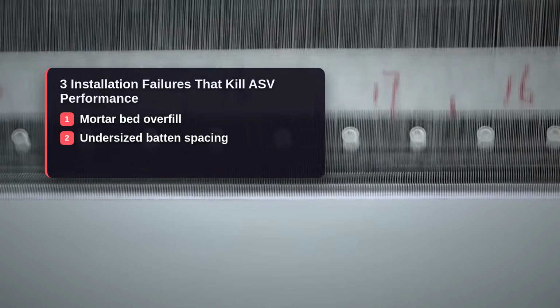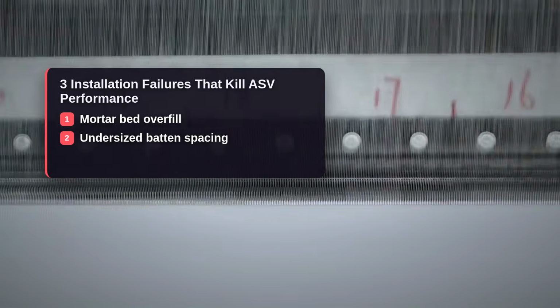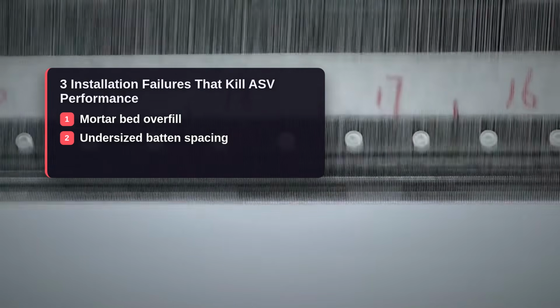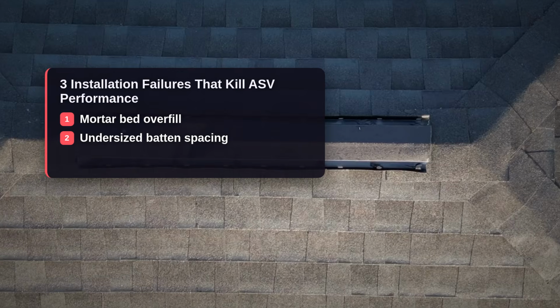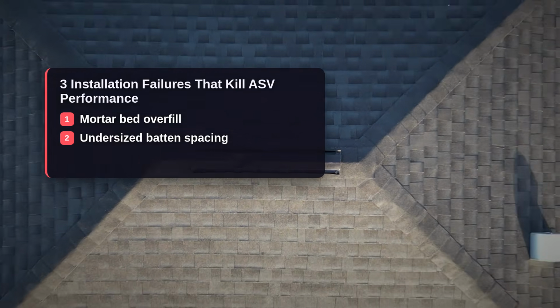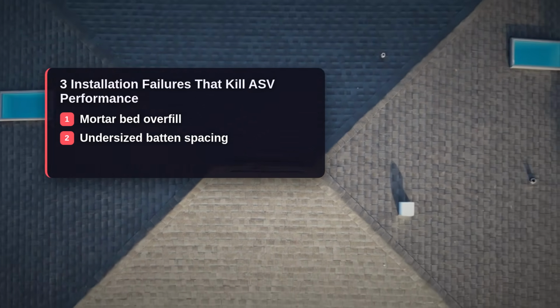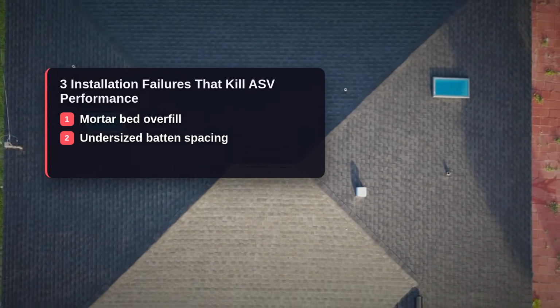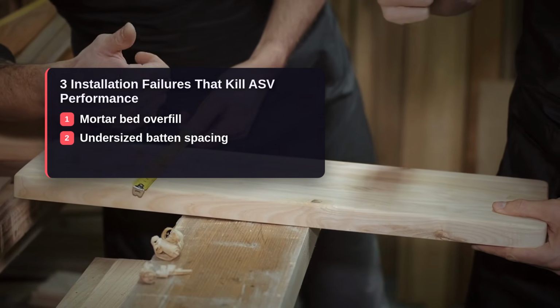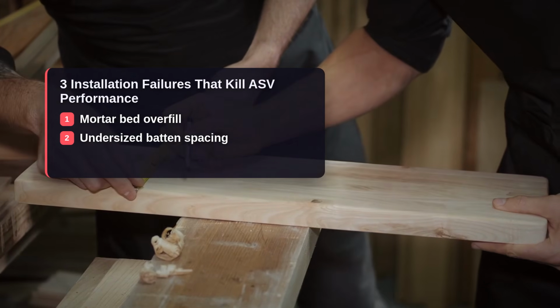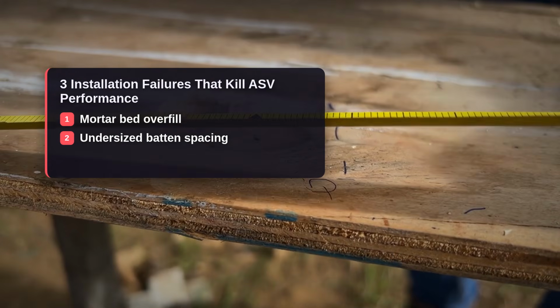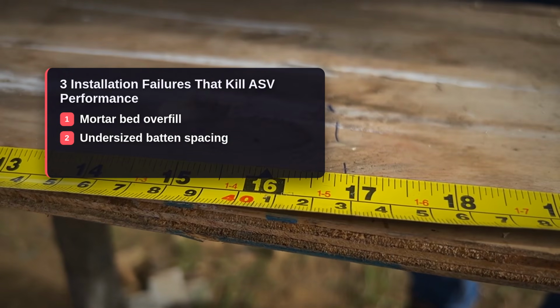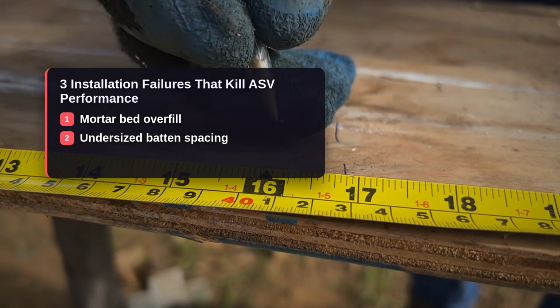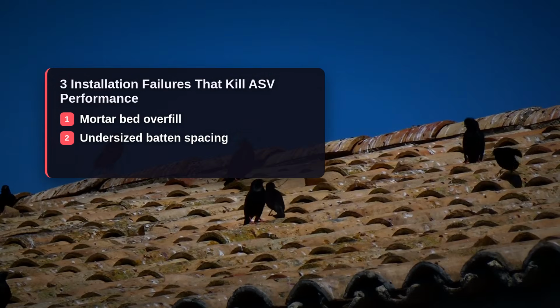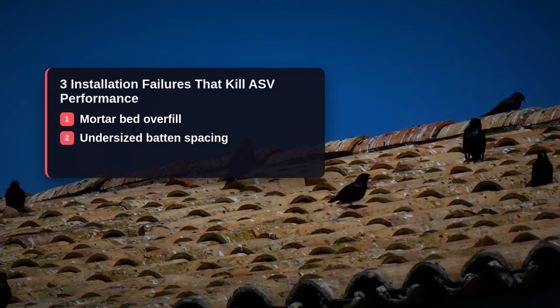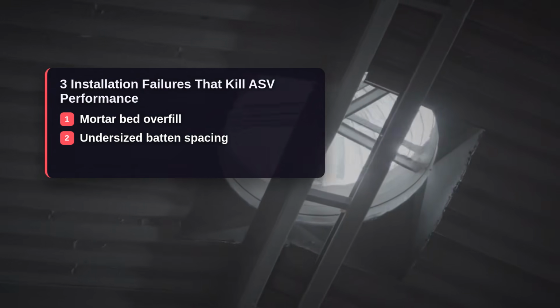The second installation failure is batten spacing. Clay tiles are typically installed over horizontal wooden battens, narrow strips of wood running across the roof slope, rather than directly over the deck sheathing. The batten creates the physical air gap. If the batten height is undersized, less than 3/4 inch, or if the battens are too close together and restrict airflow, the convective loop cannot develop the airspeed needed to carry heat away efficiently. The Florida data was generated with a 3/4 inch batten in an open, free-running ventilation channel. Reducing that gap to 3/8 inch was shown in supplementary testing to reduce the ASV cooling contribution by approximately 35%.